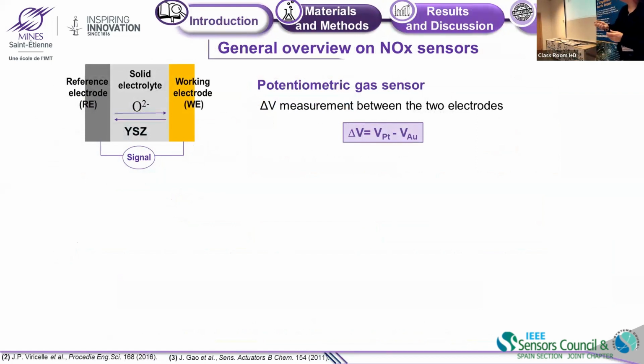Here, the electrolyte is yttria stabilized zirconia, and there are 2 electrodes, the working electrode in gold and the reference electrode in platinum. The working principle is the measurement of the difference of voltage between these 2 electrodes.